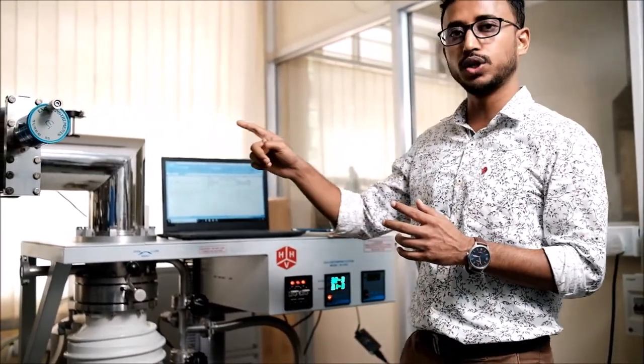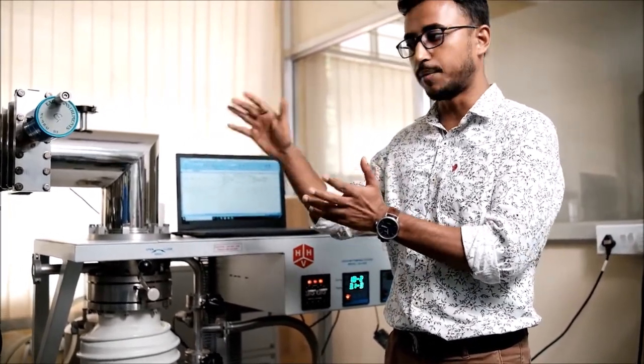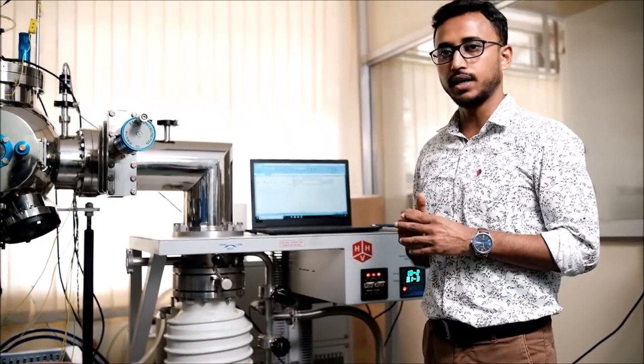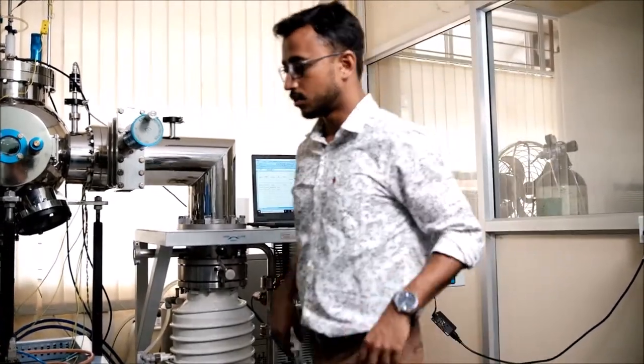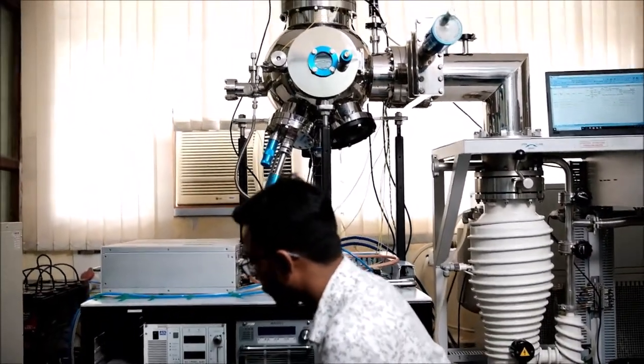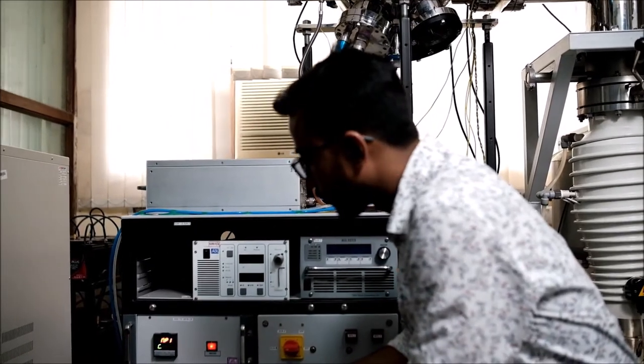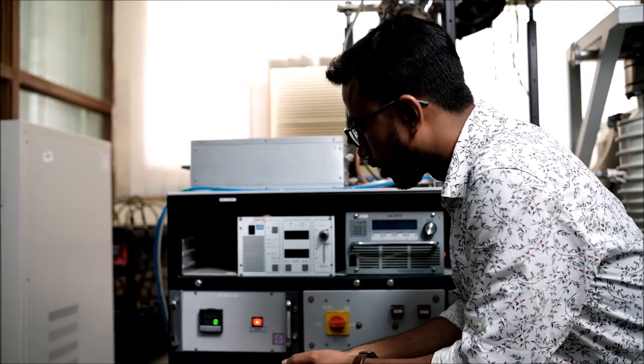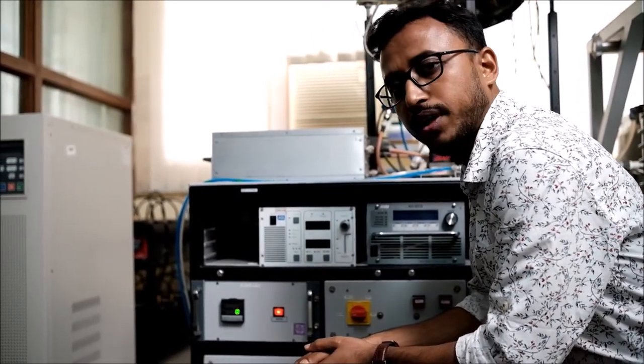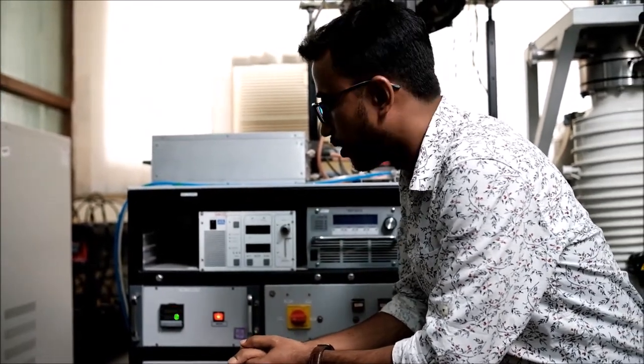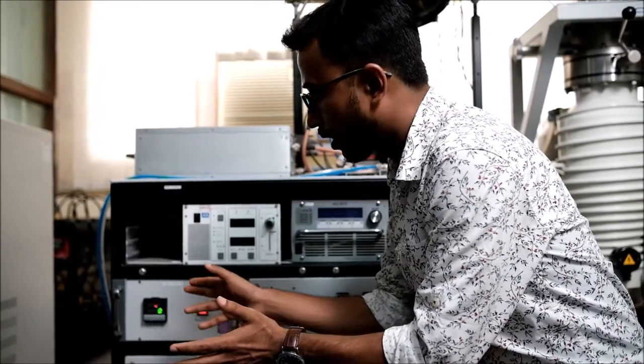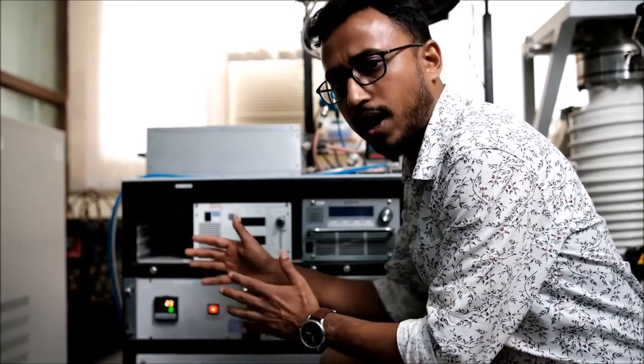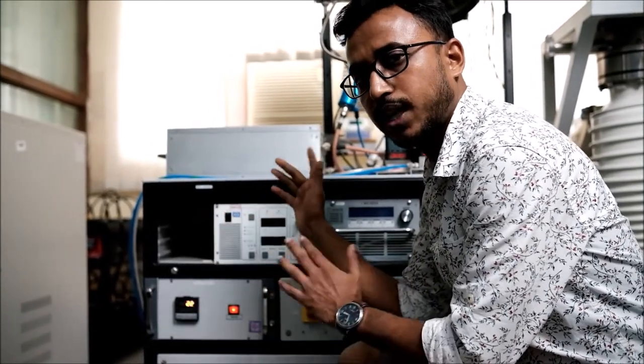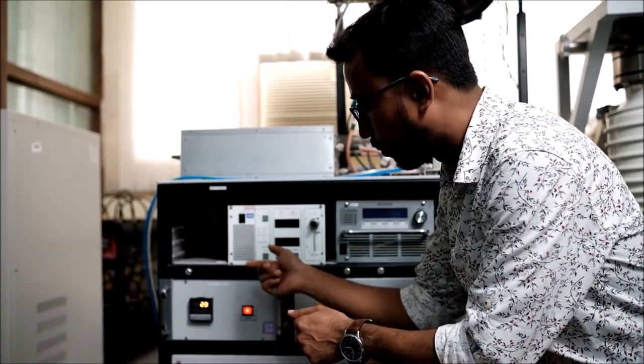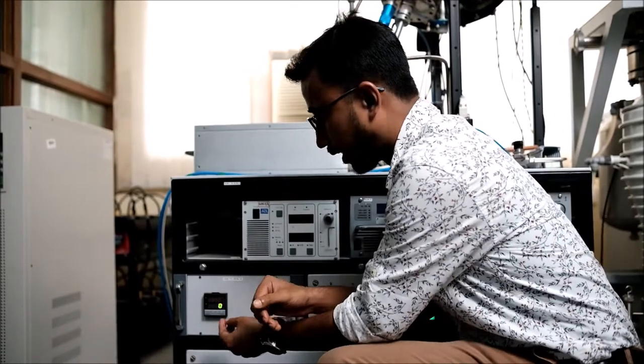Because we will do the deposition at 300 degrees Celsius, and it will take some time to reach the set temperature, we will first switch on the temperature controller, and by the time the temperature rises to 300 degrees Celsius, we will do the other part. So we first switch on the temperature controller unit. And we will set around 10 minutes to reach 300 degrees Celsius, and then I will do deposition for 30 minutes, but I will keep the program for 1 hour to stay there at 300 degrees Celsius. But once my deposition is over, I can stop the temperature through the controller.